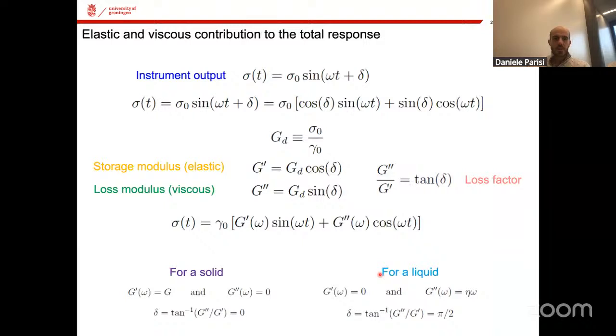Okay, so the rheometer, via software, does this very simple calculation. It takes the stress, so it expands the sine of the sum, and therefore we have in the stress two contributions. One, which is the amplitude multiplied by the product between cosine and sine, this dependent on the delta or the phase shift, and this is frequency. And then another term, which is sine of delta, cosine of omega t. So this term here and this term here can basically be called the elastic contribution, or G prime, and the loss or viscous contribution, also known as G double prime.